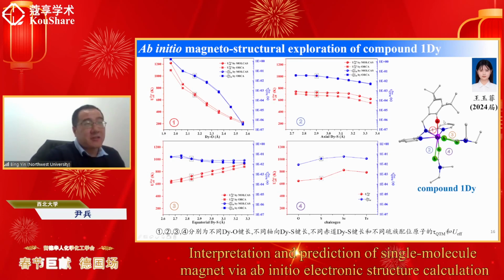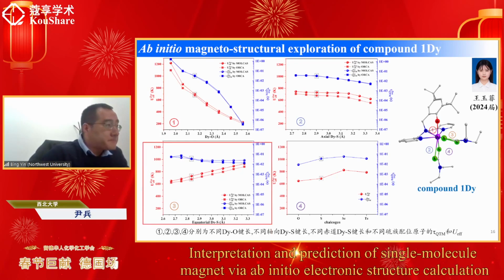It is actually related with the axial oxygen atom. The change of this distance gives the largest variation of the two important parameters. So that means the sulfur coordination does not play a dominant role, but only a supporting role in affecting the single molecular magnetic behavior of the system.